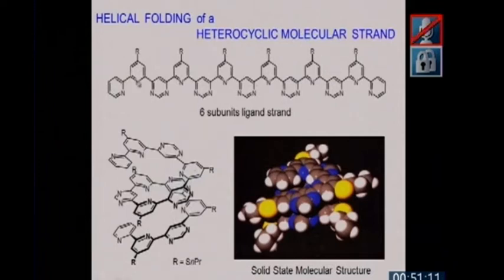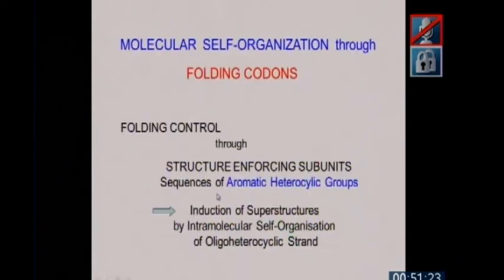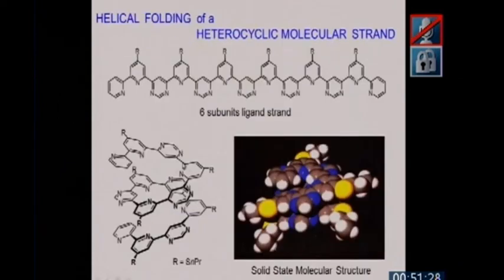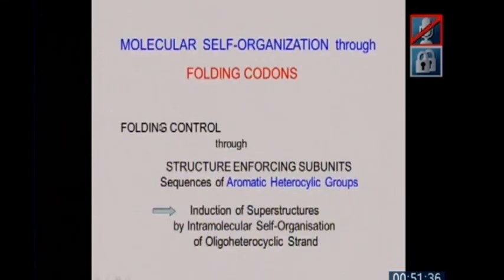That means with turning around each of these bonds, you end up with a helix, a helical molecular strand shown here. That is the crystal structure, the solid state structure of this entity. In other words, quite interestingly, this type of sequence, pyridine, pyridine, pyrimidine, pyridine, pyrimidine, pyridine, pyrimidine, and so on, leads automatically to the folding of the chain.